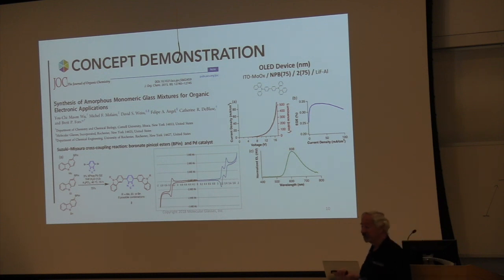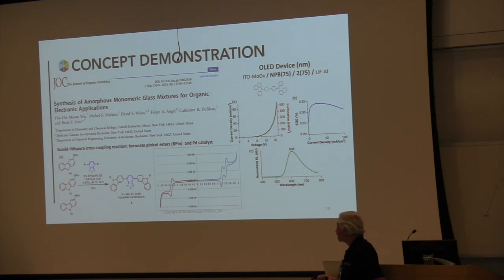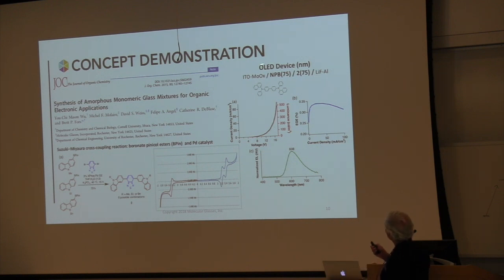So we had to make a device, which for us is difficult because we have no capability of doing that. We needed the vacuum deposition, and we needed to make a device and then test it. So we made a device. The device was a simple hole transport layer, and our material, sandwiched between 2 electrodes, and we put a field on it. Typically it's 5 to 10 volts, which comes out to about 5 times 10 to the 5th volts per centimeter. So pretty high fields. That enables the charge injection. And it lit up. As you increase the current, the luminance went up. Very low quantum efficiency, but we're just trying to demonstrate that it works. So this is a demonstration. We published this in the Journal of Organic Chemistry, 2015.